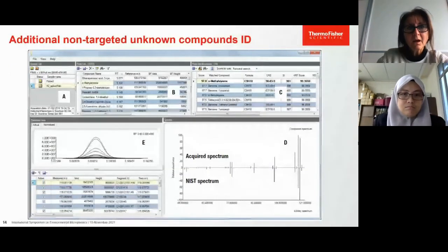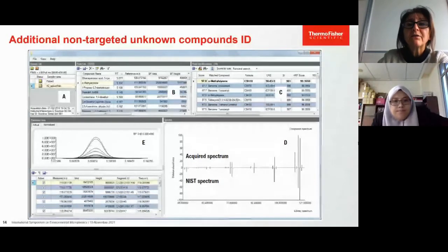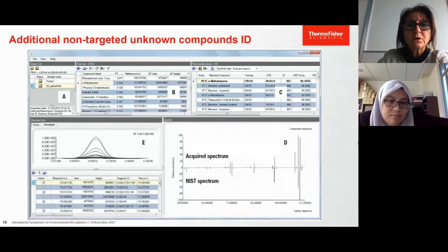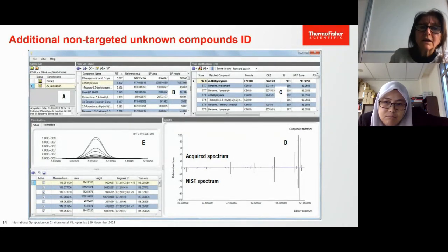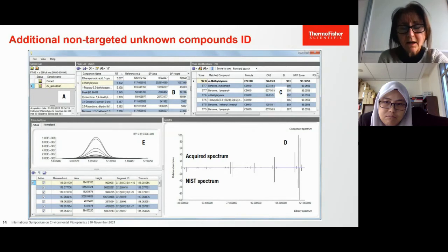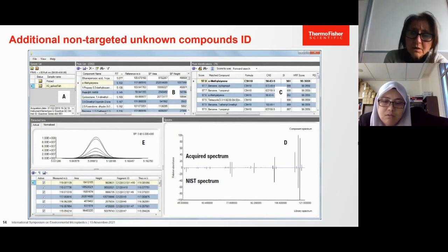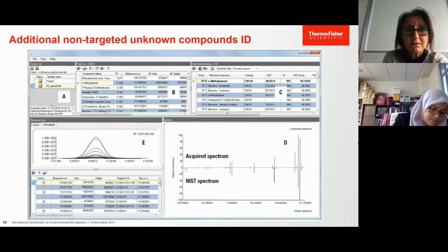used. In this study, the Thermo Scientific TraceFinder chromatography data system was used on samples on the GC Orbitrap. In addition to the target quantification, TraceFinder allows for untargeted analysis in a routine full-scan high-resolution mode of operation. This approach allows to screen the raw data acquired for the quantitation experiments with the possibility to search additional chemicals resulting from the pyrolysis process. An example is shown here for the alpha-methylstyrene, a well-known degradation product from the polystyrene pyrolysis.